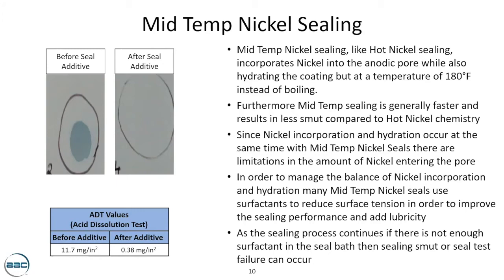One, it's being done at a much lower temperature, 180 degrees, and the type of surfactant that is being used is different. And for those two differences, mid-temp sealing has become a lot more popular. It's generally faster than your hot nickel seal, and it results in much less smut than your hot nickel seals would.